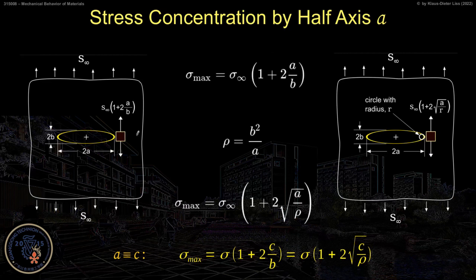I repeat that here again: the stress concentration by the half-axis A or C is shown here, that sigma max equals sigma infinity times 1 plus 2 square root A over rho. Or if we express it in A and B instead of A and rho, then we have the formula here at the top - because rho, you may want to remember, is B squared over A.